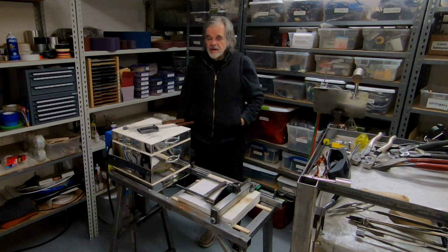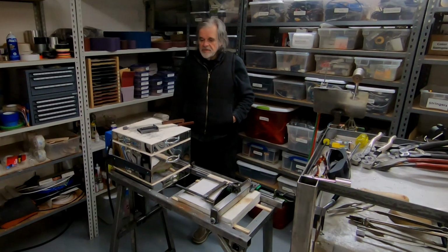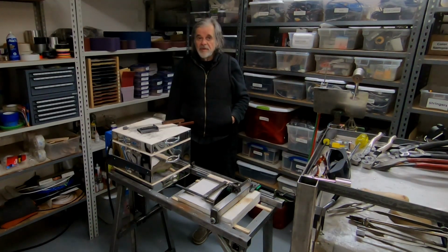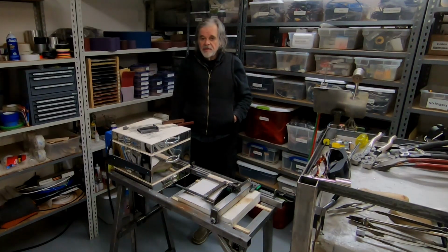So I changed the set point to 2000 so that when the piece is out of the kiln, it can recover to a fairly nice higher temperature. I take the piece out of the kiln when it gets to like 1500, then while I'm working, the kiln recovers to roughly 1750 or something like that on its way to 2000. When I put the piece back in after working on it for a little while, the kiln drops down to like 1525 or so, and that means that it takes a little bit less time for it to recover to 1550, 1600 or so when I take it back out again.